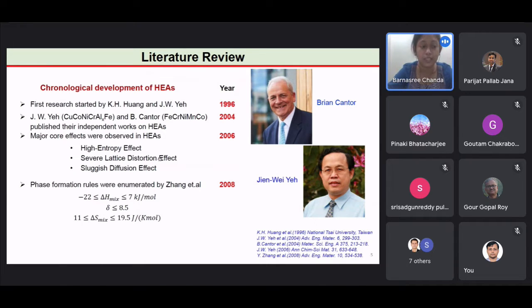In 2006, the major core effects were observed. That is the high entropy effect, and the severe lattice distortion effect, which is due to the presence of various kinds of atoms and their difference in atomic size. And the sluggish diffusion effect, due to the presence of various multi-principal elements. The diffusivities in such alloys are expected to be slower. Therefore, kinetically, they restrict the formation of complex phases.